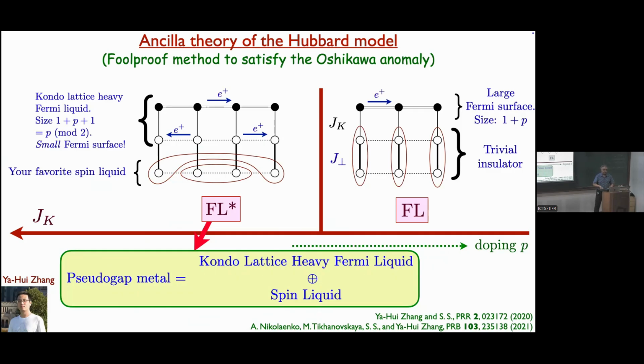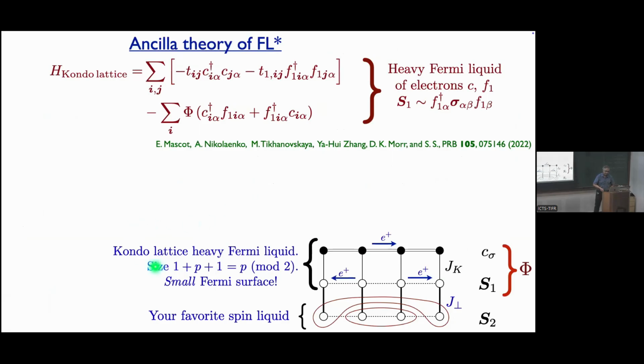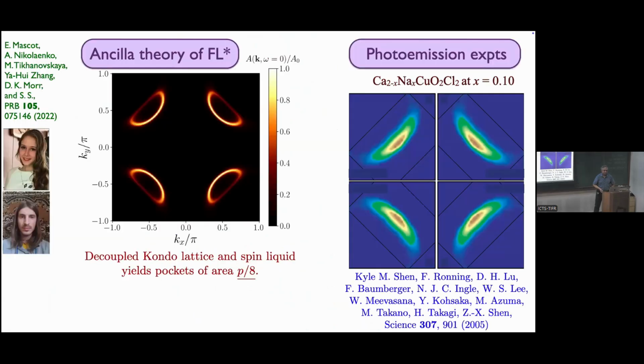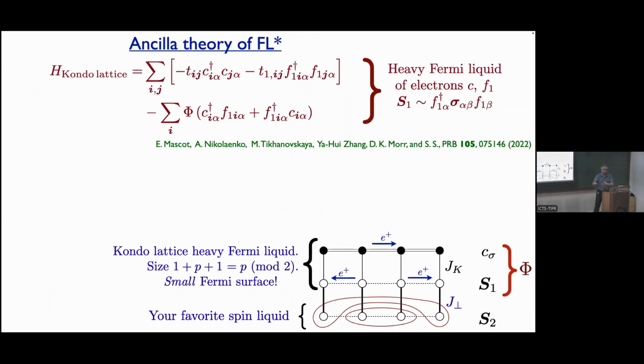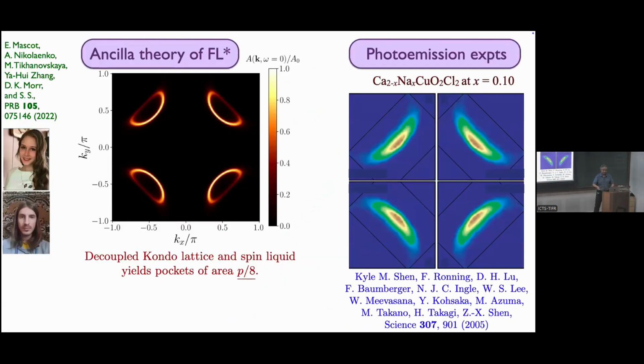Okay, so let me, however, for now, ignore the bottom spin liquid, which could be any spin liquid you want at this point. Just look at the top two layers. Well, the top two layers are exactly the Kondo lattice model I already showed you, in exactly the same notation, and I just have to study it for a different density of the C. So when you do that, you do get 4 pockets of area p over 8 for appropriate parameters, which you can fit to the data. So these parameters are T1 and the phi. Those are completely determined by this computation, for example. And the area is exactly p over 8, not anything else.